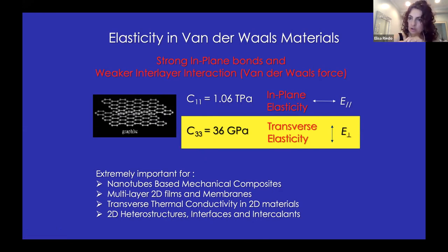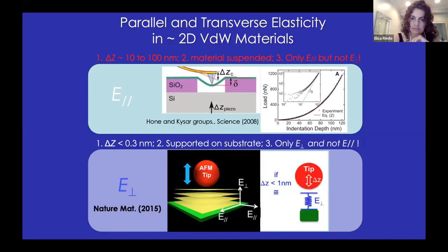So this high anisotropy in the mechanical properties and also in the electronic properties gives rise to many interesting properties in this material. And while quite a lot of studies have been done on the in-plane elasticity of these materials, think about all the elasticity measurements done for example on graphene or other 2D materials deposited on membranes, where atomic force microscopy tips are used to indent and then measure the elastic properties, much less is known on the transverse properties, and in particular, what is happening in between the layers, right?